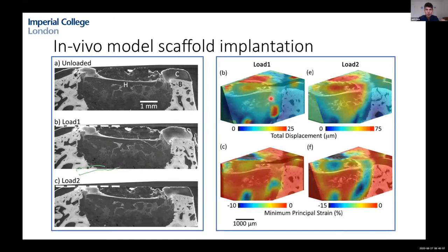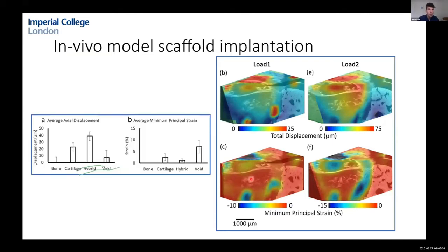Although the implant placement wasn't as intended, it was interesting to look at micromotion and the relative motion of the implant to the surrounding tissue. The displacement results showed the void around the implant had lower stiffness than other components and took the majority of the strain. At the second loading level, most of the displacement occurred in the actual hybrid implant itself.